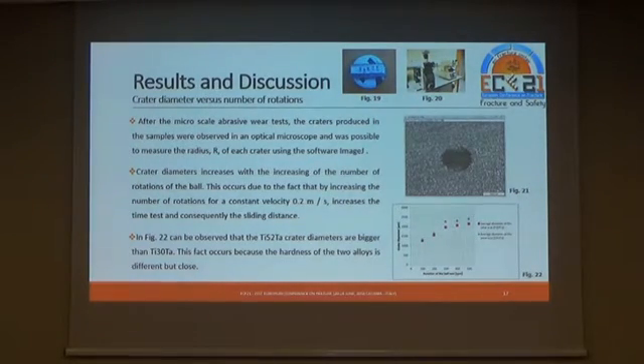Crater diameters increase with the increasing number of rotations of the ball. This occurred because, by increasing the number of rotations for a constant velocity of 0.2 meters per second, the test time and consequently the sliding distance increase. In figure 22 it can be observed that the titanium 52% tantalum crater diameters are bigger than titanium 30% tantalum. This fact occurs because the hardness of the two alloys is different, but very close.